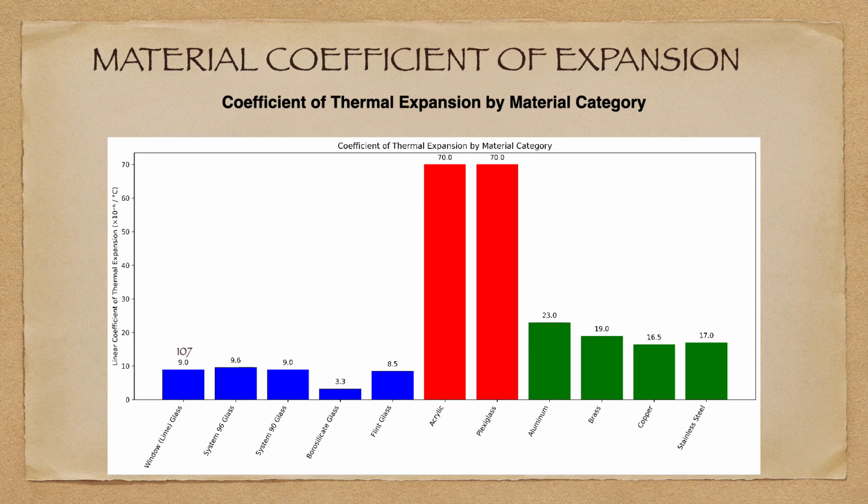However, for our purposes, glass tubing, when it is being sawed, may have a higher temperature secondary to the friction of the saw blade on one part of the glass, whereas the remainder of the glass is much cooler, and therefore inducing stress to the material and inducing cracks or breakage.